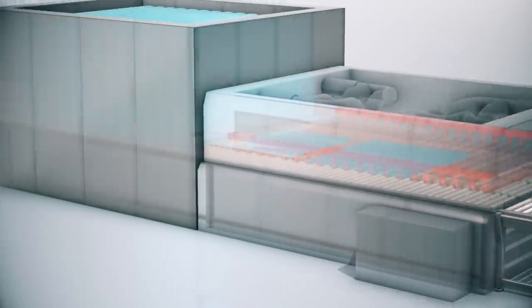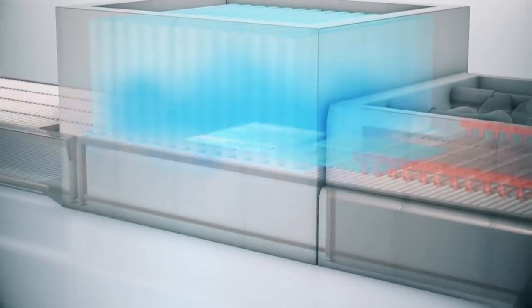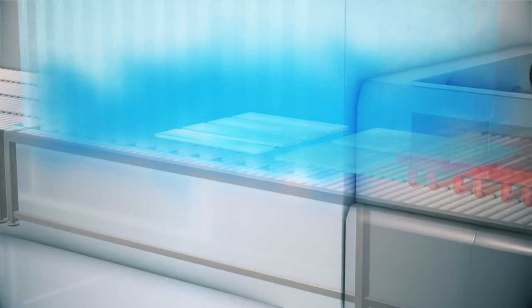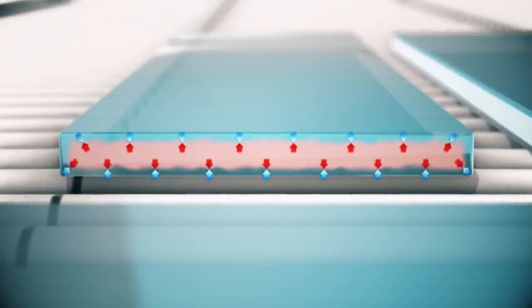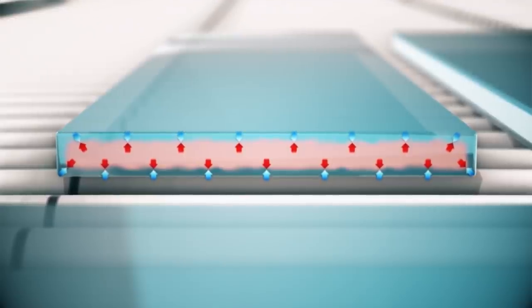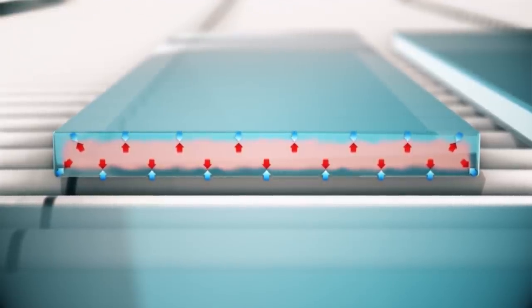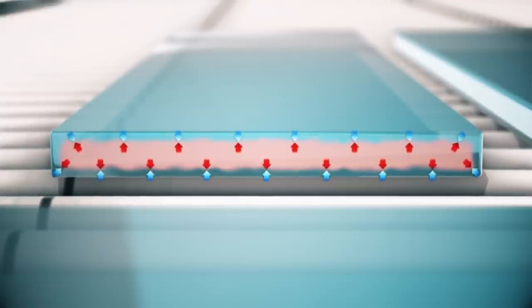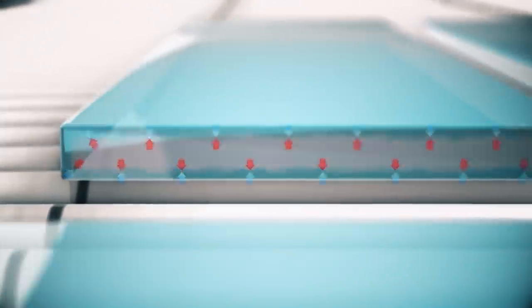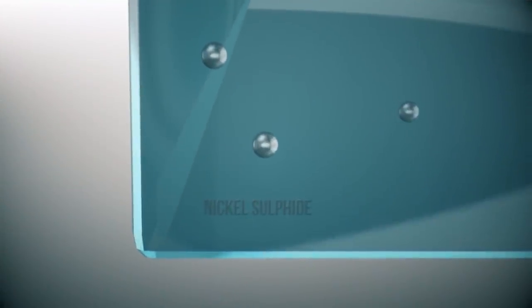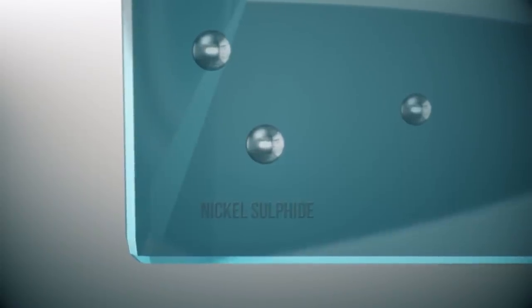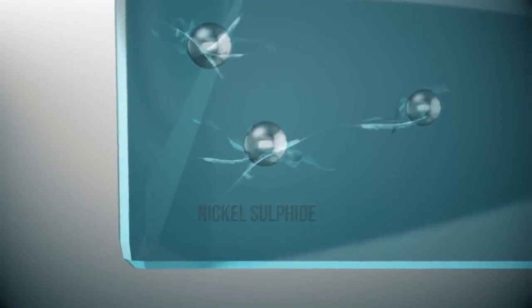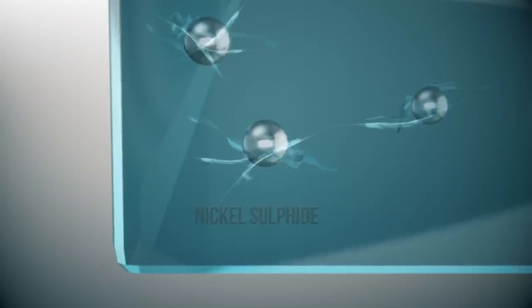The trouble arises when glass moves to be rapidly cooled. Cold air is blasted to cool down the outside of the glass faster than the inside, compressing the surface and creating tension within. This is what makes tempered glass stronger than normal glass and changes its break pattern. But rapid cooling also traps the nickel sulfide in the hardened glass. Over time, the nickel sulfide will expand, creating micro cracks, which can cause the glass to shatter without warning.